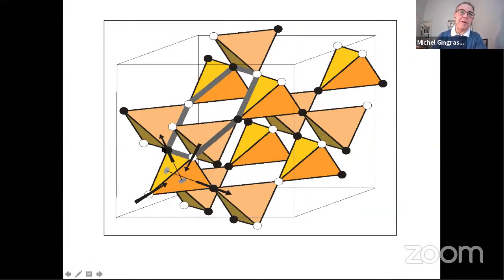And so this is, as I said earlier, a spin ice configuration. Each tetrahedron has two spins pointing in, two spins pointing out. They obey the ice rules. And so what we do now, we flip that spin, we break the ice rule, but then we fix it immediately by flipping this side here and this side here, flipping this one, this one, this one, and going around in a closed track this way, we end up flipping six spins and we return to a ground state that obeys the ice rules. This is the lowest excitation.